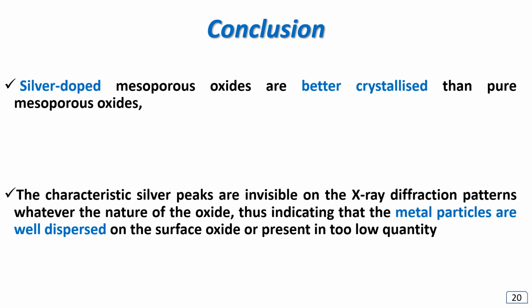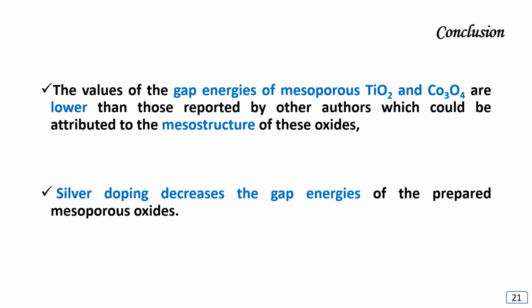The characteristic silver peaks are invisible on the X-ray diffraction patterns, whatever the nature of the oxide, thus indicating that the metal particles are well dispersed on the surface oxide or present in too low quantities. The values of the gap energies of mesoporous titania and Co3O4 are lower than those reported by other authors, which could be attributed to the mesostructure of these oxides. Silver doping decreases the gap energies of the prepared mesoporous oxides.